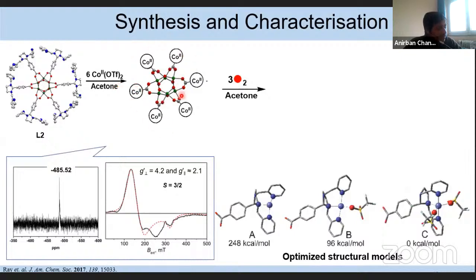The same type of reaction was done with the hexanuclear ligand L2, to form a hexanuclear cobalt complex. This cobalt complex was also characterized by 119Sn NMR, which shows a sharp singlet at minus 485 ppm, exactly similar to the free ligand NMR. So that also confirmed that the stannoxane core remains intact after complexation.